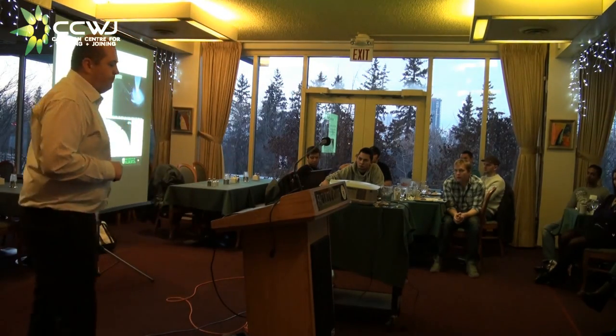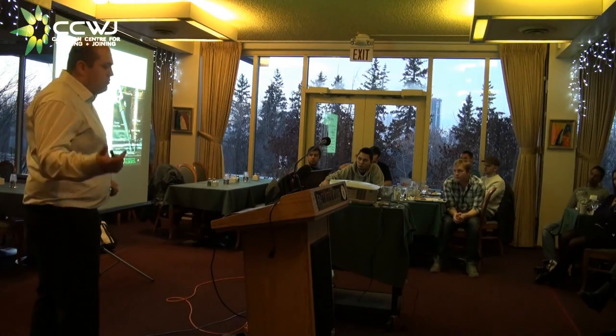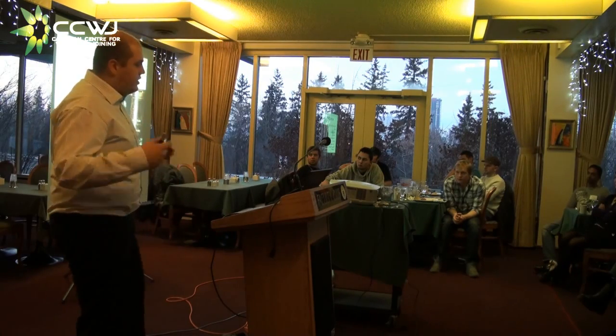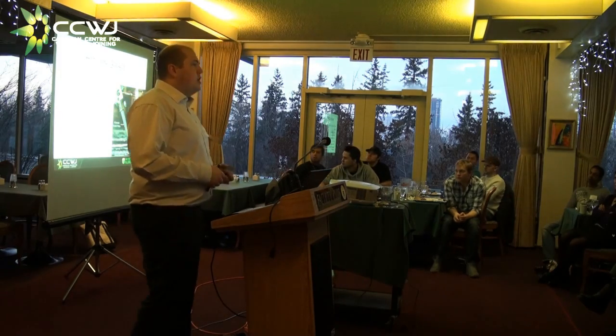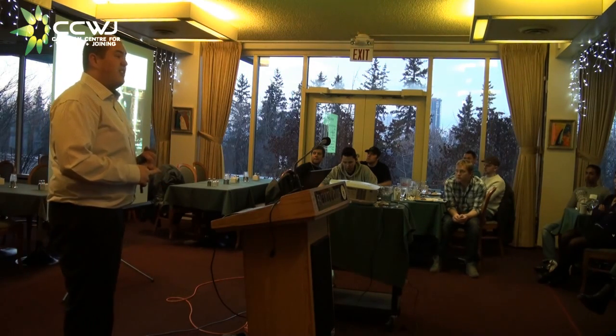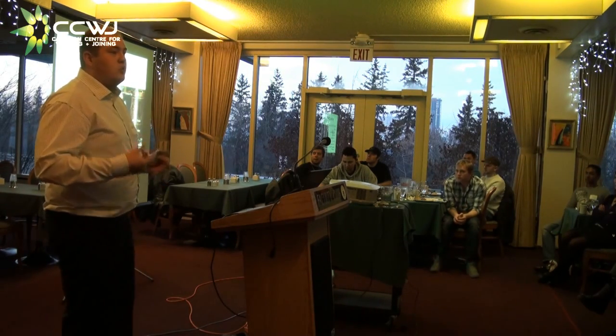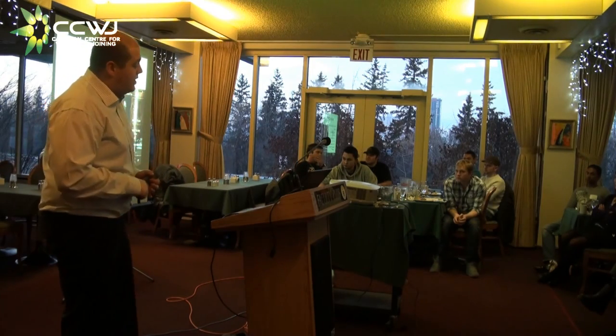Industry cannot use it. That's where I said, well, why don't we just switch out the TIG for a MIG torch? Now we can use 2 consumables, have higher productivity, and who cares if we contaminate the MIG torch? It'll just end back up in the weld pool anyways. Everything's good. So with our MIG torch, since we want a stable metal transfer, we want to use a thicker wire. We want to use short circuit transfer so we don't have too high of heat, so we don't dissolve those tungsten carbides.